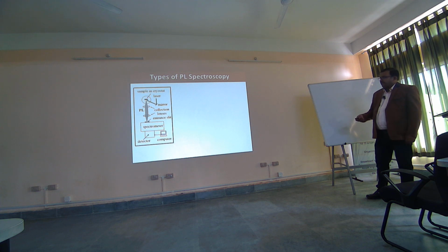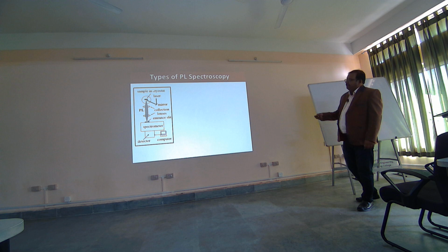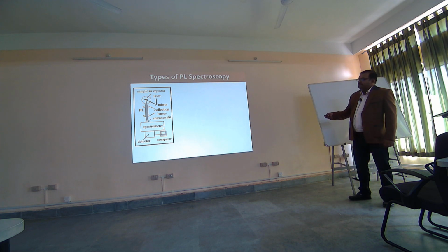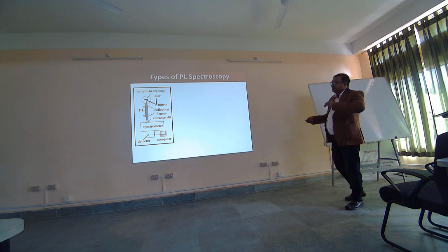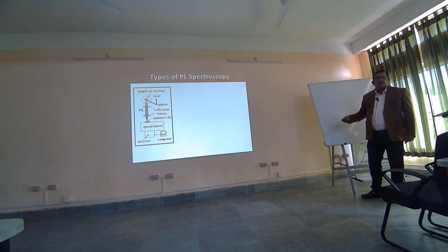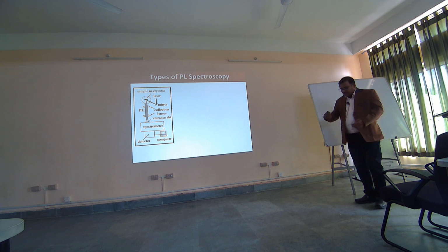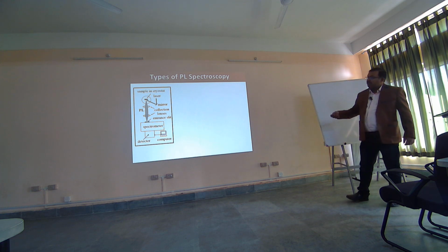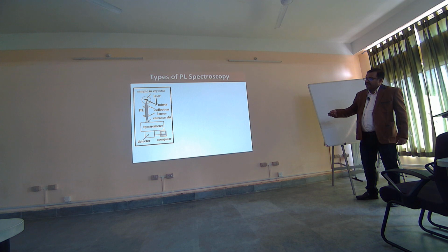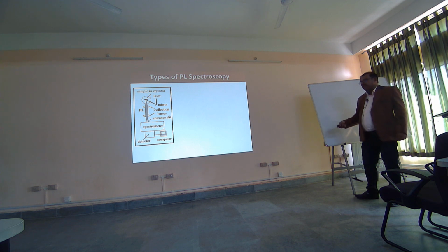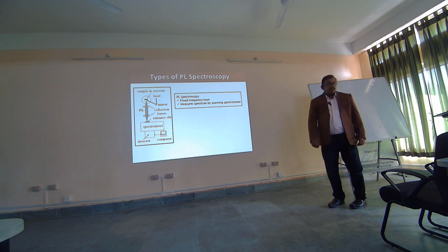Again, if I look into the experimental setup of a photoluminescence spectroscopy, what we do is we use a laser which excites. This laser is shone onto a mirror and then diverted to a sample. My sample is here inside the cryostat, and once the laser strikes the sample, it excites. If the energy of the laser is larger than the band gap of the material that we are trying to characterize, it will excite the material, and that will lead to formation of electron holes. And when these recombine, that gives rise to emission of light, and that emission is captured by means of these lenses onto the spectrometer, and then it is recorded.